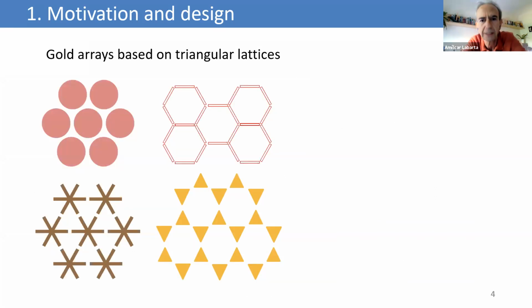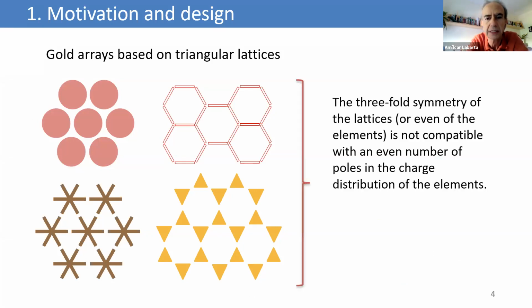So we want to take advantage of this threefold symmetry of arrays of gold nanoelements based on a triangular lattice in order to hinder the excitation of the near-field modes. The idea is to transfer this energy, or to favor the excitation of the collective modes, which correspond to sharper and narrower peaks. So our main point is to use the fact that the threefold symmetry is not fully compatible with an even number of poles, which is the usual situation when we have a near-field excitation between elements which are in close proximity.